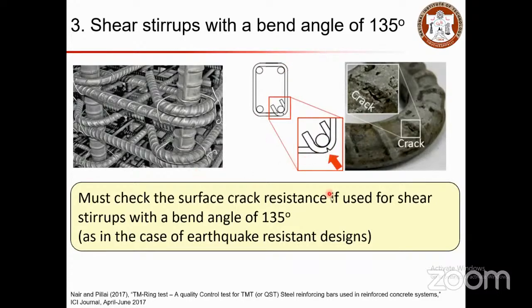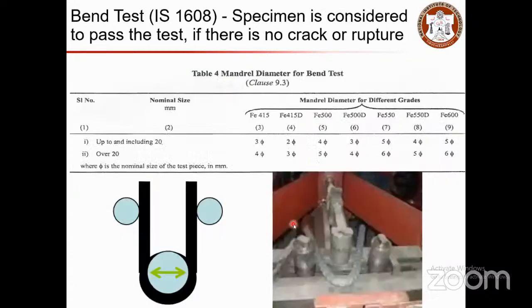So as a quality control check, the code suggests you bend at a 135-degree angle, and if there is no crack, then it is good to be used as shear stirrups. If there is a crack, then you need to be precautious and take additional care to prevent any issues, especially when you are going to use it in earthquake-prone regions, right? So in such cases, these things are very crucial.